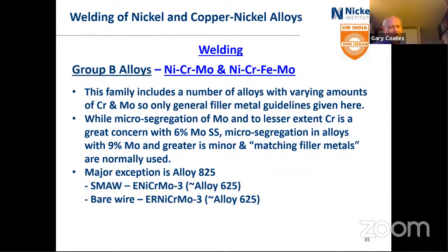And typically we do use more matching filler metals. The exception to that is the 825, which is almost always welded with a 625 filler metal. There is a matching 825 one, but it is not commonly used. It's more used where you know that there's a problem with high nickel. And there are a few cases in fuel cells and things like that where high nickel can be a problem.